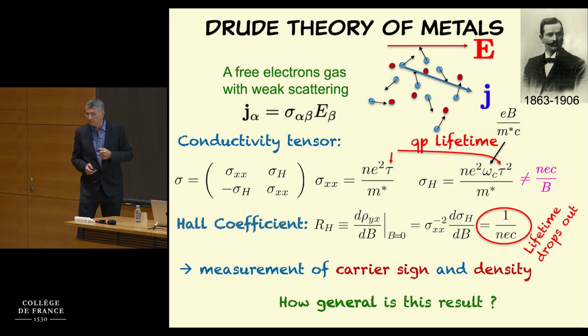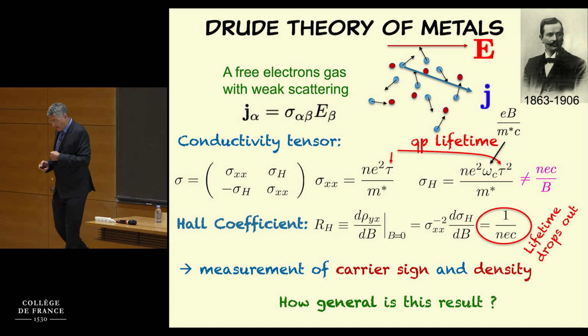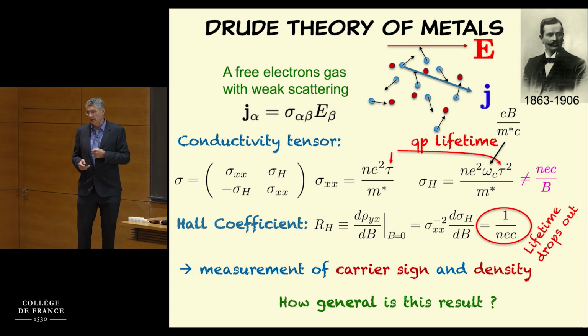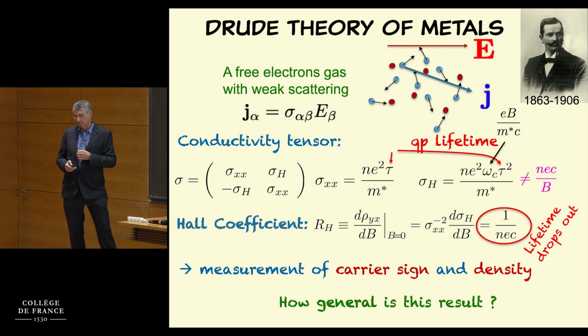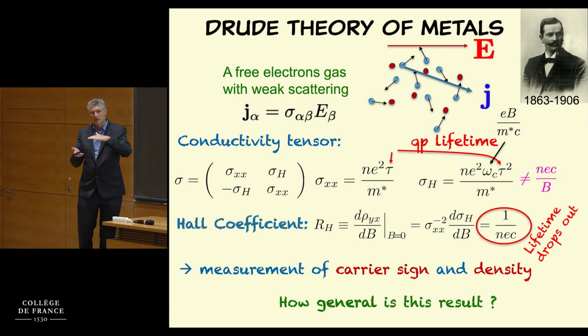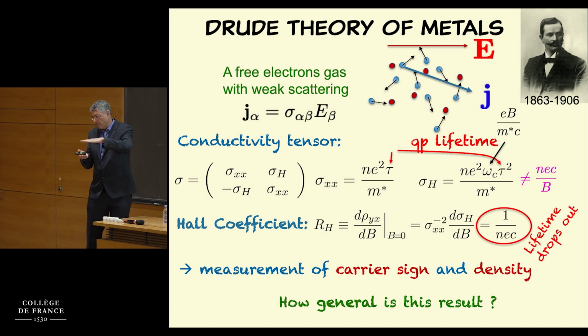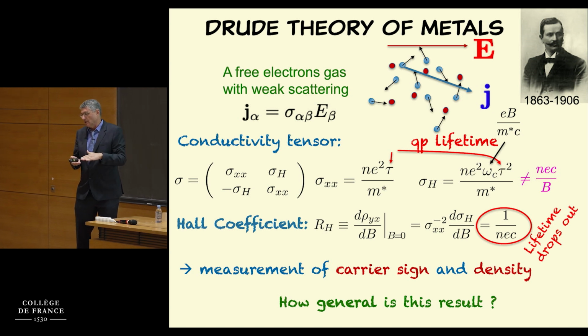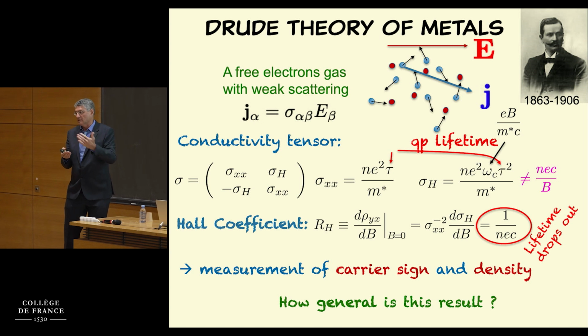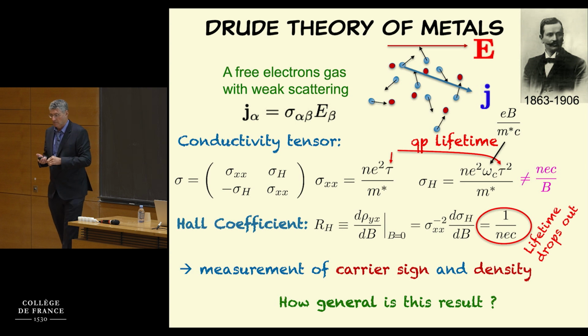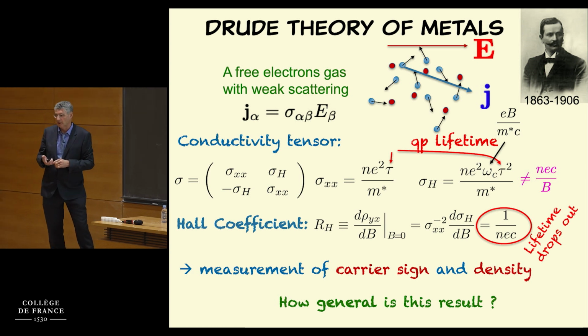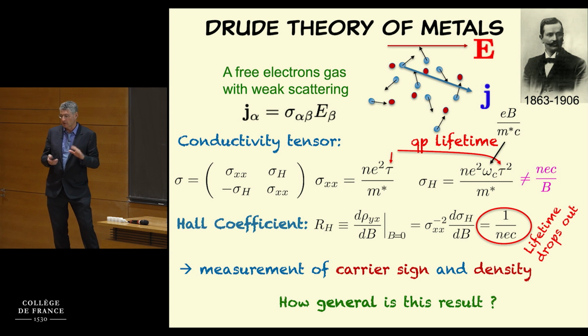Assa, maybe a question about this. As soon as you have one more band, right, then you have to add in parallel the Hall resistivity. Ratio of lifetimes. Yes. Or also, if you have two layers, because resistivity is non-additive. If you have two layers and they have different Hall coefficients, then you have to know the difference in their sigma xx. Right. But what I'm trying to say is that as soon as you have one more band, the Hall number is actually a transport measurement and not purely thermodynamic. Okay, so let me qualify the statement that I'll show later. That's when you have a single component system. Yeah.